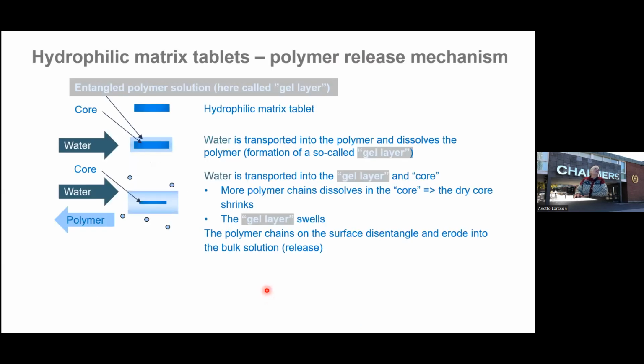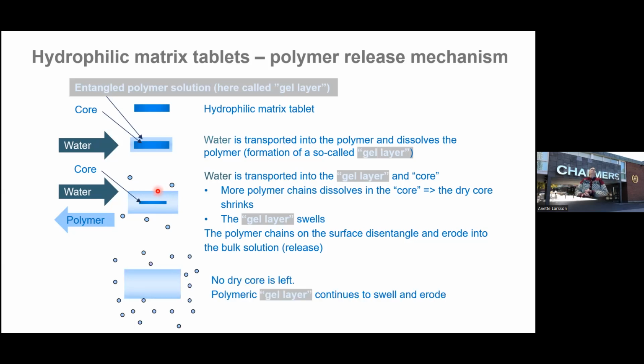So if we go back to this picture here, we still have not discussed the drug. We focus just now only on the polymers. So you can see that the water still penetrates and continues to dissolve the core. So the core diminishes. And here on the surface, you have swelling and the water is transported into the gel layer and diluted more and more until it reaches the overlap concentration where it is released and disentangles and erodes from the surface. That we call erosion when it is released from the surface of the gel layer. And water continues to penetrate and we have no core left. And in the beginning, the polymer gel layer swells and at a certain time, the erosion rate is faster than the swelling rate, and therefore we get a diminishing of the core layer, and in the end we have no tablet or matrix left.